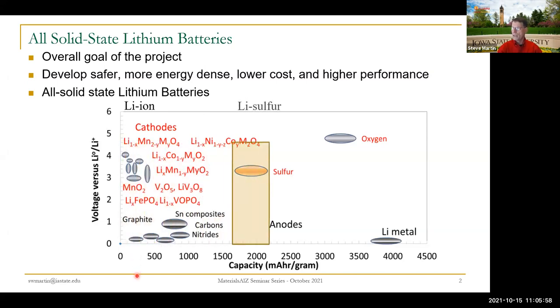If we go to a lithium metal anode and partner it with a sulfur cathode, sulfur being incredibly abundant as a result of our petroleum industry, it lowers the voltage a little bit from a typical 4 volts down to 3 volts, but the capacity goes up dramatically because the composition is Li2S. So one sulfur can store two lithium. So the capacity goes up, even at a little bit of a cost in voltage and therefore energy density, but it's about a factor of four up from lithium ion. Many people are working on lithium sulfur, but the ultimate end game here is lithium air. These would be air breathing batteries.